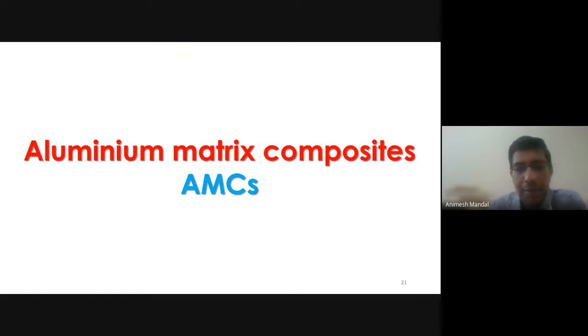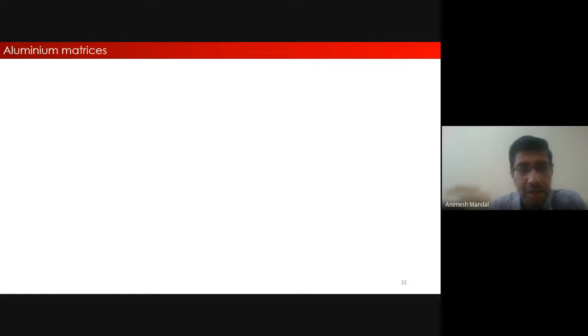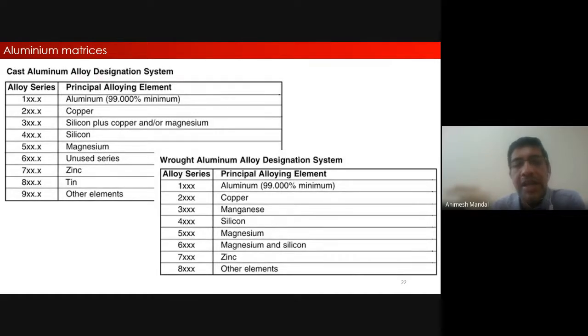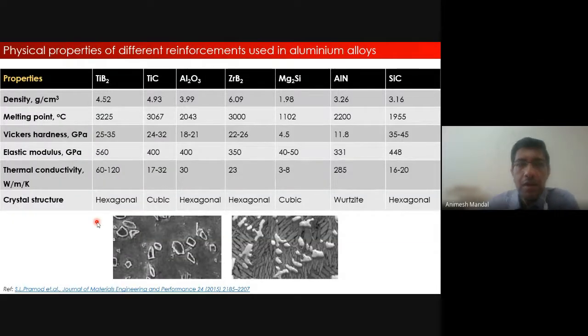Coming to your aluminum matrix composites, as we have already discussed, you can use any matrix for that matter. Whether you want to produce a cast metal matrix composite or a wrought aluminum metal matrix composite, you can choose the matrix as per your need or the application. Some of the very common reinforcements, and their properties, are shown in this table. These are quite common: titanium diboride, titanium carbide, alumina, zirconium diboride, Mg2Si, aluminum nitride, and the most common being silicon carbide.